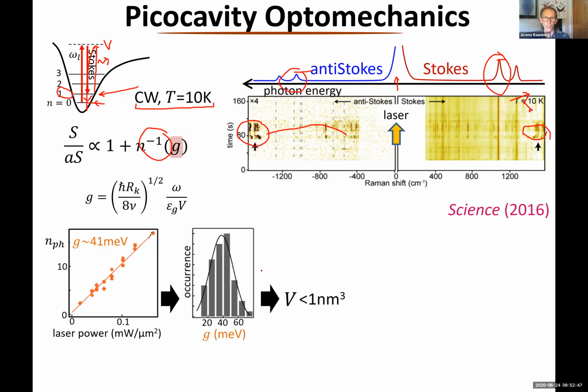This started us on a track of trying to figure out what was going on. The nice thing is that, because I said this G, this optomechanical coupling, depends on 1 over the volume, and we know all the factors in here, we can do a power dependence very rapidly as soon as we see this. From the number of photons we get out, we can extract this G for a particular one of these lines. In this case, the G that we found was 41 millielectron volts.